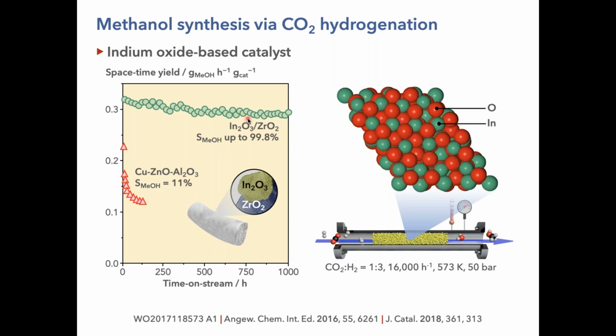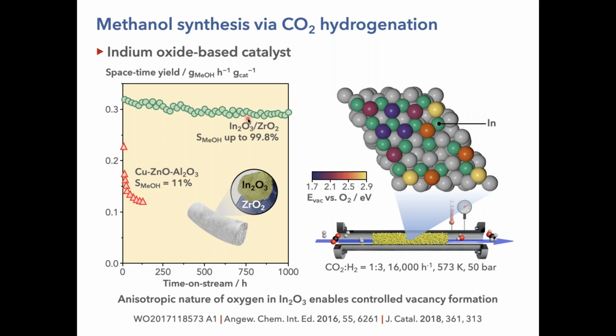The design of this catalyst was attempted from the point of view that we were convinced from the very beginning that we needed reducible oxides where we could control the vacancy chemistry, so that we are able to create coordinatively unsaturated sites at selected places of the solid without leading to over-reduction of the surface, so that we can orchestrate the reaction in a selective manner. And indium oxide is a very good example because it's extremely anisotropic. So it has very different oxygens on its surface. Here you see different oxygens with different colors.